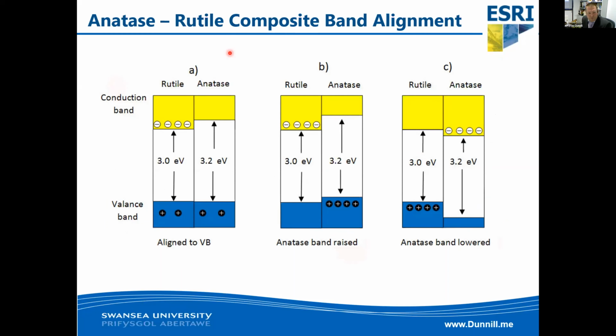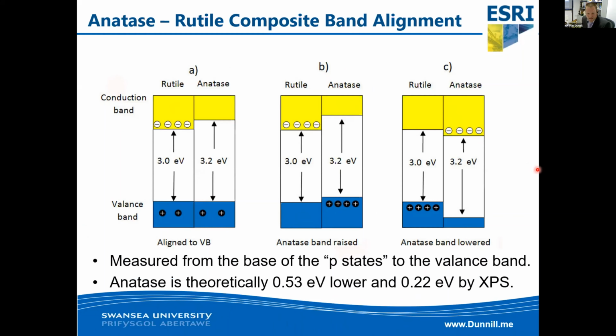So there are 3 possibilities when you align the band gaps of these 3 systems, thinking back to my circular diagrams earlier. You can align the valence band, and you see that you've got a 3.2 versus a 3 for anatase and rutile. You can have a raised anatase or you can have a lowered anatase. And the computational guys all said it was a lowered anatase. The experimentalists all said it was a raised anatase, until we came along with our samples that actually showed that it is indeed a lowered anatase.